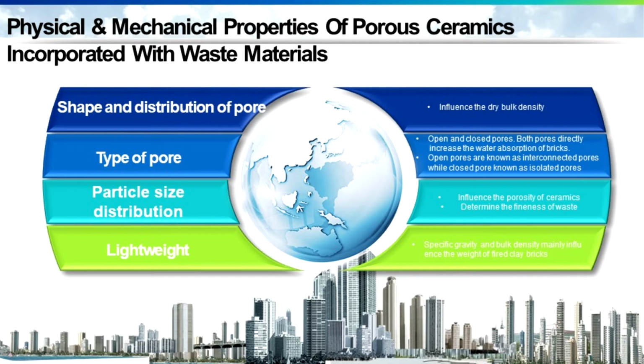Another important property of waste is the particle size distributions or PSD, which influence the porosity of ceramic. The PSD can be used to determine the fineness of the waste. In addition, the specific gravities and bulk density of the waste would also influence the weight of fired porous ceramic. For instance, it was reported that smaller specific gravities and bulk density of sludge waste indicates a reduction in the dry weight of the final porous ceramic.